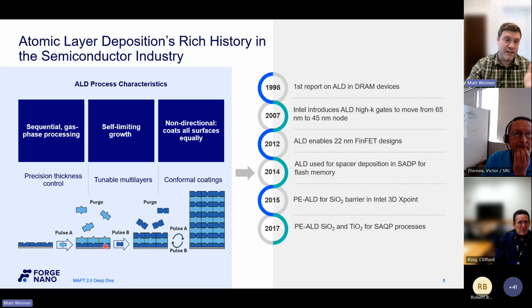This self-limiting growth nature is where that perfectly conformal idea comes from, which is, I think, the most common aspect that people think about with ALD. The asterisk there is if you wait long enough, if you're getting the species to where it needs to go, then you'll actually do conformal film. So this is a non-line of sight technique. It provides quite a high quality of film.